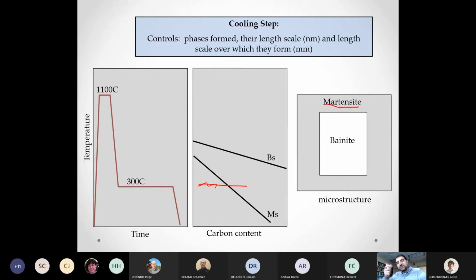So we can invert the situation. We can have martensite on the outside and bainite on the inside if we use a step cooling approach. So many possibilities are available to us. And we can now control, as I mentioned, a new length scale, which comes from the duration of the decarburizing step. And we can control the phases that form through control of the cooling step.